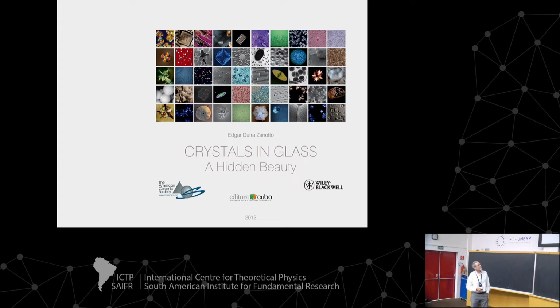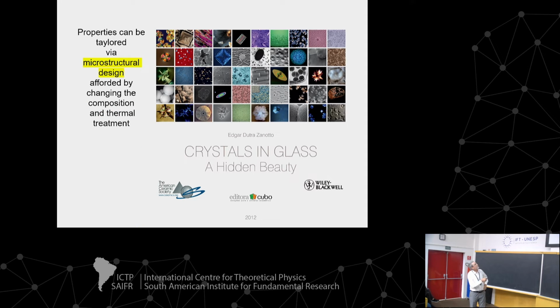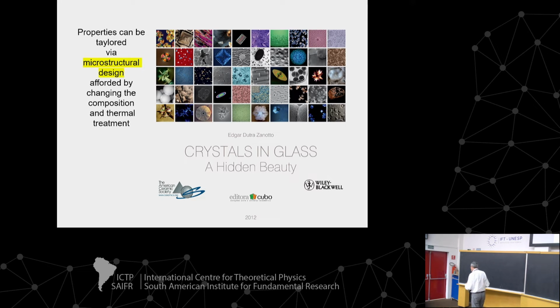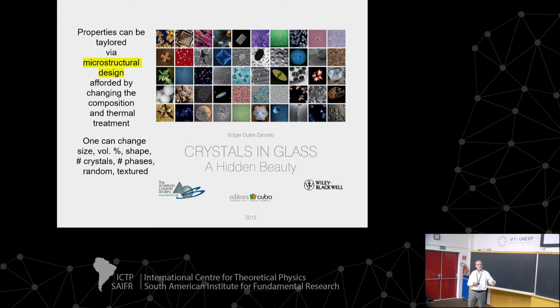And my favorite area: glasses are unstable, so you heat them up in a certain controlled way. You crystallize glasses. You change the structure completely and improve many properties. And these are microstructures. Looking through a microscope, these are crystals nucleating and growing in different glasses. By what we call microstructural design, you can control the shape of these crystals, their number, their volume fraction, the type, their chemical nature, the size distribution. You can control the properties, combinations of properties.